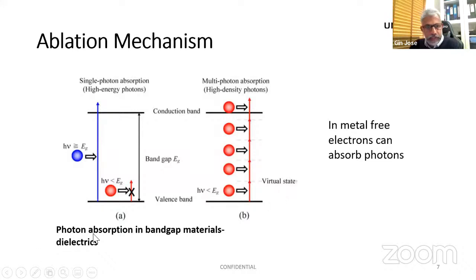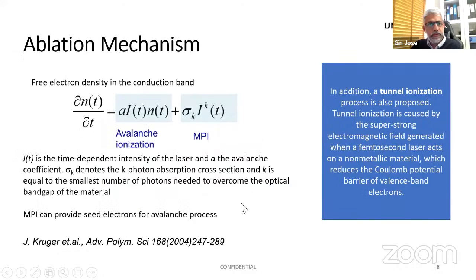Most of the experiments that I described here are happening in dielectrics. In a metallic material, you can have direct excitation or removal of electrons. Here in a dielectric material, this multi-photon absorption is one important aspect. You can also have impurities in such materials, which can also produce direct ionization. So it's essentially the production of electrons by the excitation process in an intense pulse, which leads to the ablation of the material from the surface of a dielectric material.